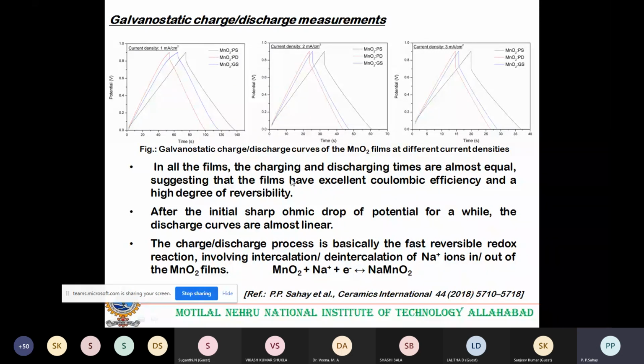The second: after the initial short ohmic drop of the potential, for a while the discharge curves are almost flat. You see there is a little bit of potential drop. This potential drop arises due to the internal resistance of the film. And if you increase the current density, this drop is more. Very common thing, V is equal to IR. So if I is increasing, the V is increasing. So this drop is more. Here it is further more because it is 3 milliampere, compared to 2 milliampere or 1 milliampere. So this drop is because of that.